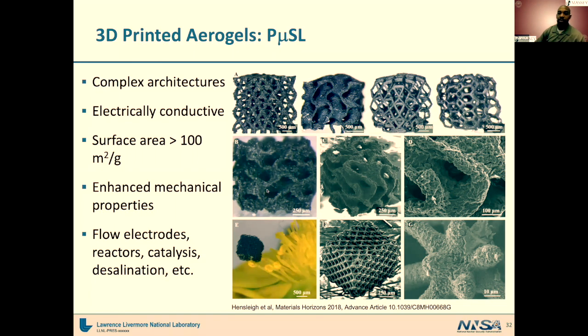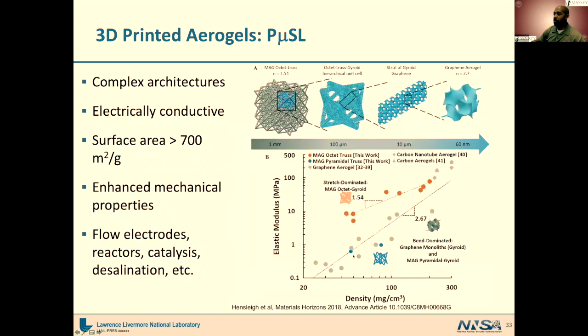And when you do this, as I mentioned before, you typically have the superlinear dependence of porous materials' modulus on things like density. But you can actually start to shift that dependence. So here, it's close to 2.6, which is common. Shifting it to something more like 1.5, so it's a much lower dependence now, when you start to incorporate some of these complex sorts of architectures. So moving forward, we're looking to use some of these materials for things like flow electrodes, reactors, catalysis, and desalination.